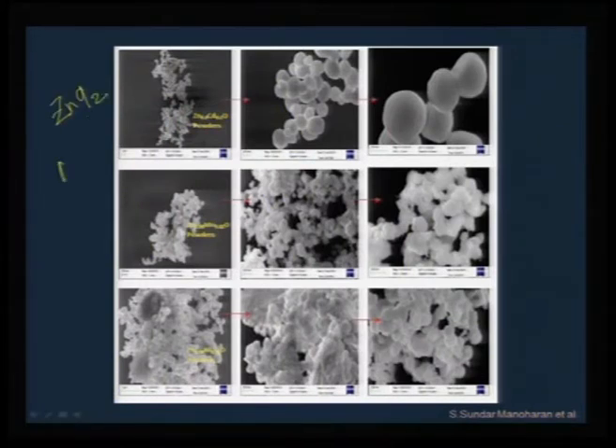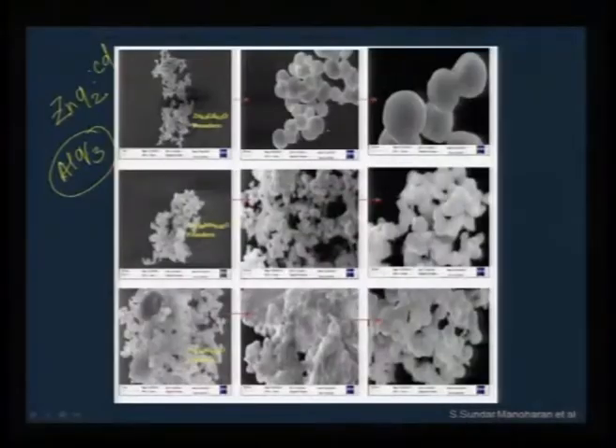This is something similar to AlQ3, what we have seen in the previous two slides. Zinc Q2 is a potential precursor. Again, using the concept of solid solution, we can dope cadmium in ZnQ2, because cadmium Q2 and ZnQ2 are isostructural. So if you put one in other, you do not see any phase segregation, and this can act as a very good precursor for cadmium doped zinc oxide.